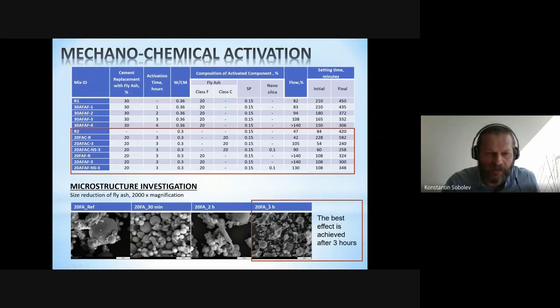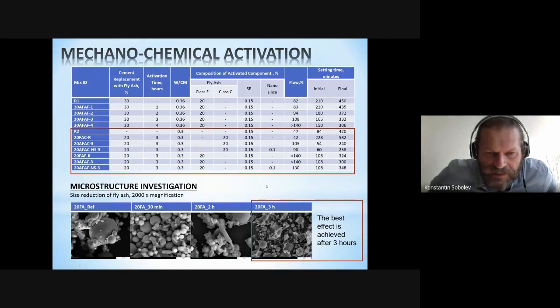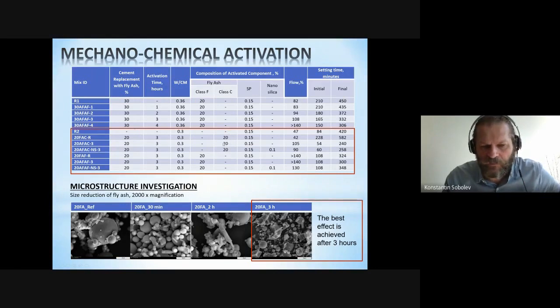as well. But the major improvements were expected with class C, which is suitable as a precursor and for formation of beneficial structures during mechanochemical activation. Again, we tried 20% of activated material, same as Portland cement, and we activated it for the optimal time of 3 hours. And all the materials were processed and produced. Mortars were produced at water to cement ratio of 0.3.